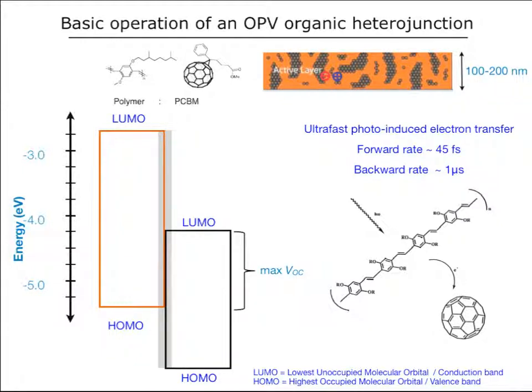So what is the photophysical mechanism for operation of the devices? Well, we can do at least a little cartoon picture here. So we excite in one of the materials, typically the polymer, which will be the stronger absorbing material. We excite an exciton, which is this bound electron-hole pair. The exciton is bound by a little bit of extra energy. That's why you see this dip in the LUMO level and a little increase in the HOMO level.